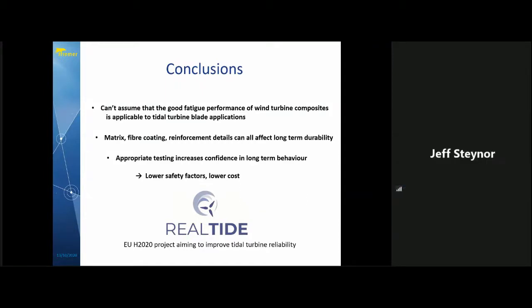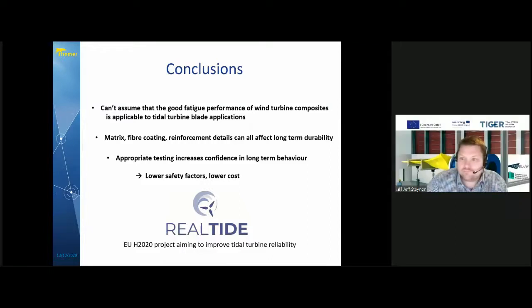Okay, so we haven't considered X tomography yet, but the definition of a failed blade is a reduction in stiffness by 10% in the IEC standards. So as we monitor with strain or DIC and pick up that change in stiffness, we can identify a blade failure.